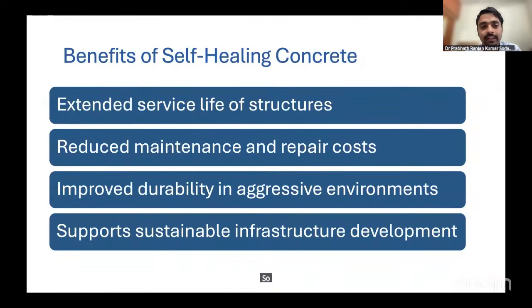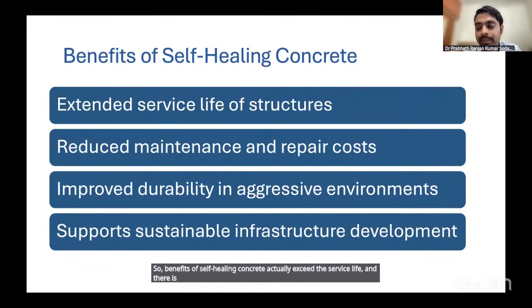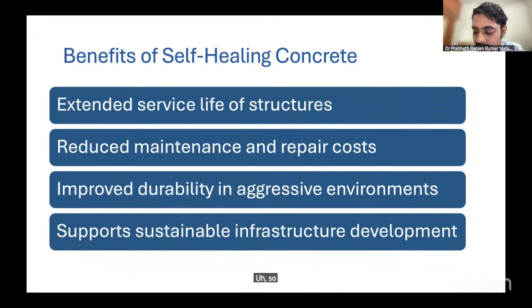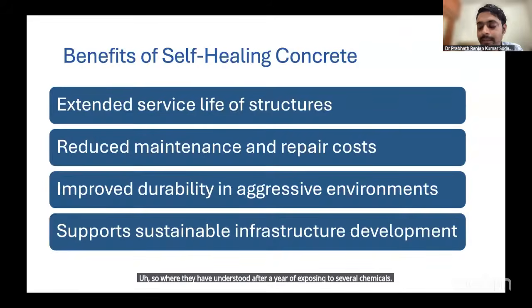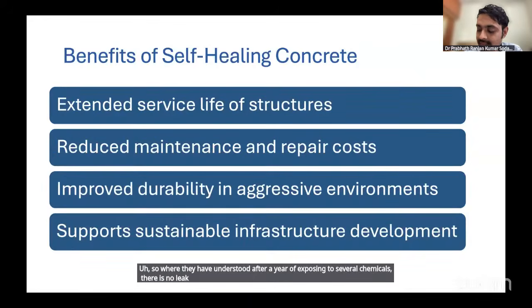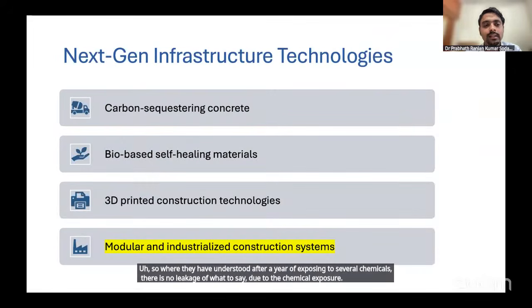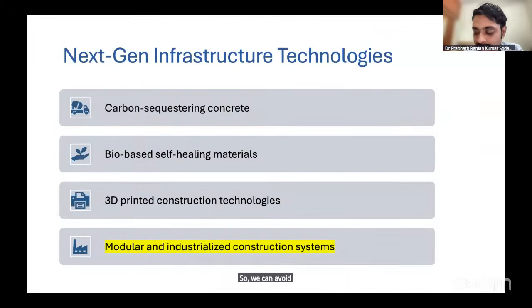So the benefits of self-healing concrete include extended service life, and there are already people experimenting in Denmark. They have constructed a beautiful structure, a 1,000 square feet slab, where they found that after a year of exposure to several chemicals, there is no leakage due to the chemical exposure. So we can avoid repairs if we adopt such things.